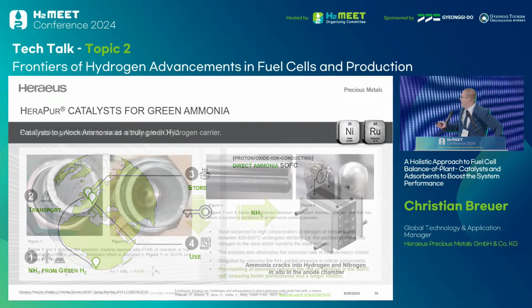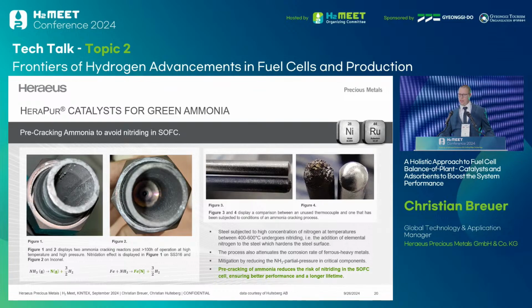Nice idea. I am a bit reluctant with this process because the cracking reaction, where it takes place, also contributes to nitridation of a lot of steel components. And it just shows some pictures here that were taken from some ammonia operating systems, where we see that these materials can deteriorate under the operating conditions. And so our proposal is to rather use a pre-cracking catalyst for the ammonia ahead of the stack instead of going directly in. But of course, this is dependent on the individual operation of the system in a way.